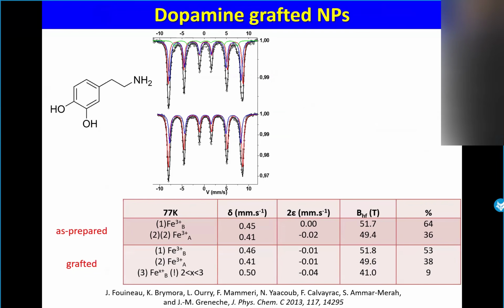So for medical application, sometimes you graft some molecules. At room temperature, the spectra was not so easy to fit. At 77K, you can see that in the presence of dopamine, in the upper spectrum, there is a third component, which is green colored. For the as-prepared sample, no problem, as expected. But for the dopamine grafted system, you can see those two first components and the third one.